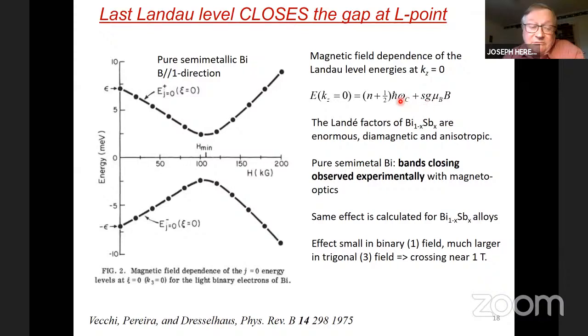The orbital energy is actually not that high. So that these two terms actually cross at a very low field of the order of 1 Tesla. And we are then in the ultra-quantum limit, already at 1 Tesla in these alloys, extreme quantum limit.